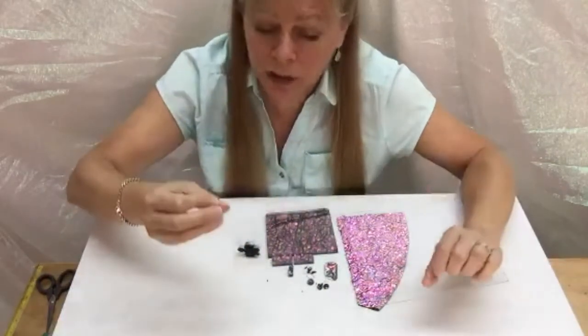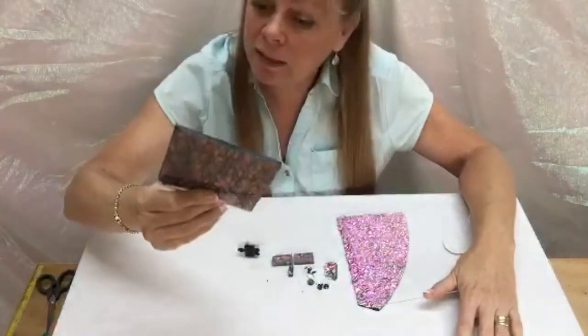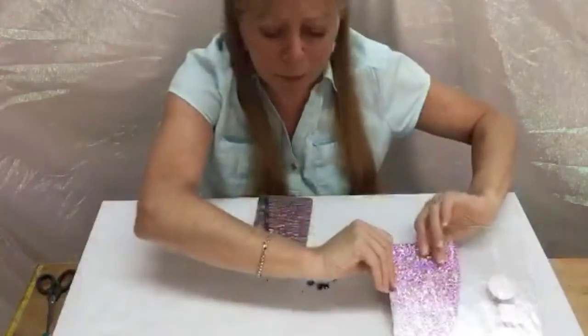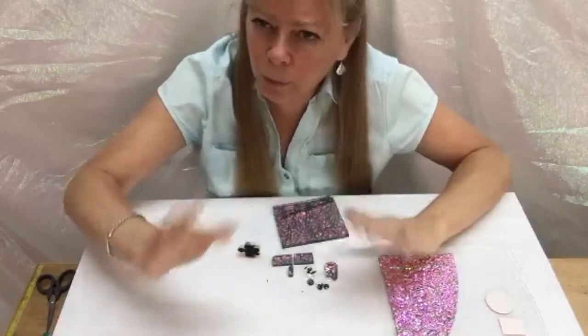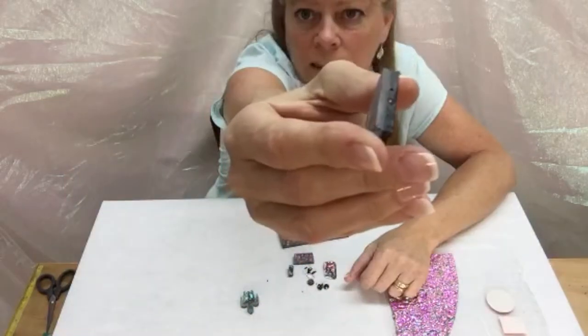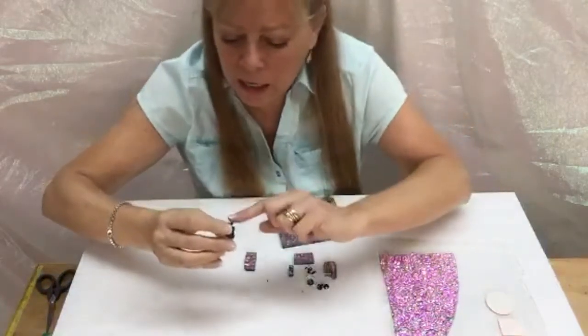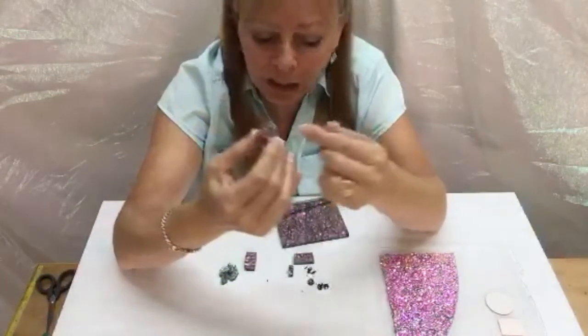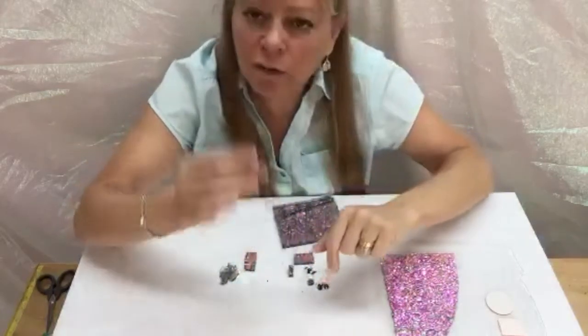The final way that happened to me was moisture getting stuck. I had made a sort of slab of glass — it was ripple glass. I needed something pink, somebody had asked for something pink. So I got my ripple glass, put some clear on top of it. One of the problems with ripple glass is it can trap air, little tiny bubbles, which aren't usually a problem. But I cut mine on a tile saw, and these little holes in the glass — when you go to cut it with a wet saw, moisture gets in there. I remember cutting this and having moisture get into one of those little valleys of the ripple glass, and I completely forgot about it, never dried it out.